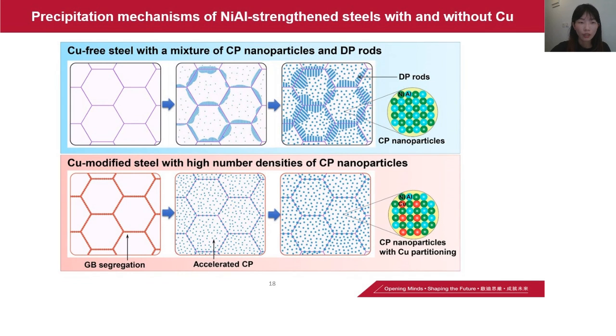So, in summary, the precipitation mechanisms in copper-free steel and copper-modified steel are summarized in this figure. On the one hand, the copper-induced acceleration of the CP reaction significantly reduces the chemical driving force for the DP reaction. And on the other hand, the copper segregation at the grain boundary can directly suppress the DP reaction.